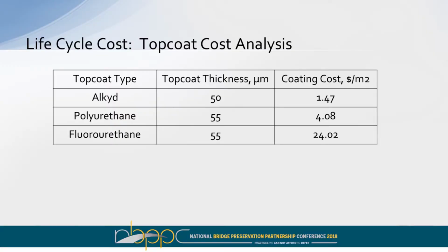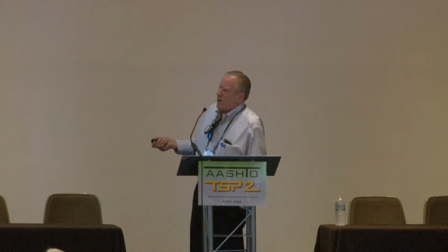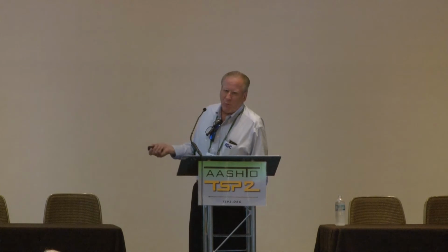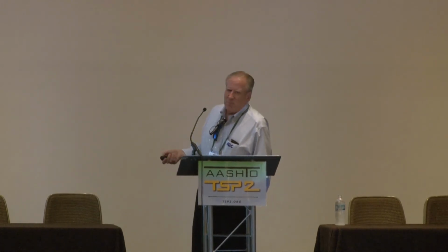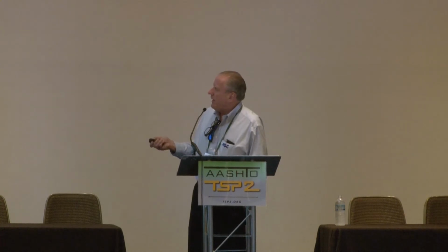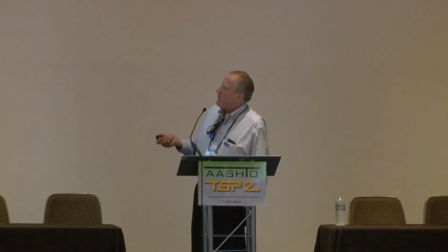So this is a kind of rough life cycle cost analysis, basically looking at top coat thickness, and then what's the coating cost in dollars per square meter. So we looked at an alkyd, a polyurethane, and then a fluorourethane. And when you look at the cost, the alkyd's $1.50, the polyurethane's about $4. Well, the fluorourethane can be 5 to 6 times the price of the polyurethane in dollars per gallon. And that's when you only consider the cost of the coating. But that's not the real truth here.